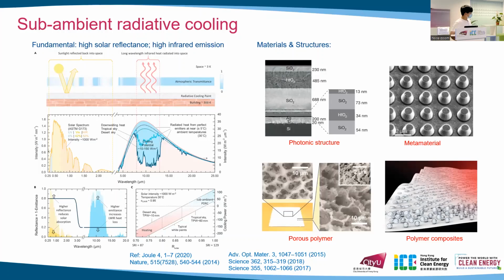The cooling potential provided from this transparent window is represented in this region. We can see that typically the cooling potential is around several tens or 100 watts per square meter. However, the sun provides power density up to 1,000 watts per square meter. So 10% of the sunlight absorption will cover the cooling potential. Therefore, a high solar reflectance is needed for sub-ambient cooling. And we can see in this figure that if the solar reflectance is lower than 90%, the cooling power is a negative value. That means we cannot cool the object below the air temperature.